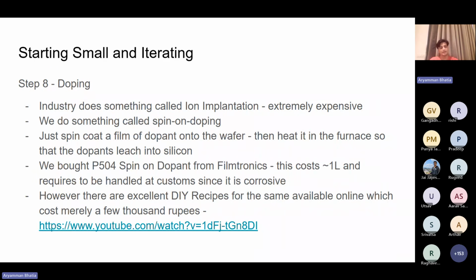You drop the chemical onto the wafer and you spin coat it using the spin coater, and that will make a layer of that dopant. In fact it's made of silicon dioxide only, so it basically forms a layer of glass on your substrate, but that glass is doped with phosphorus. Then you can put that into the tube furnace, assuming by this point you already have a tube furnace. The heat of the tube furnace causes the phosphorus from that glass to leach in and dope your silicon. So yeah, that's how you do doping, and it's a much cheaper way to do it.